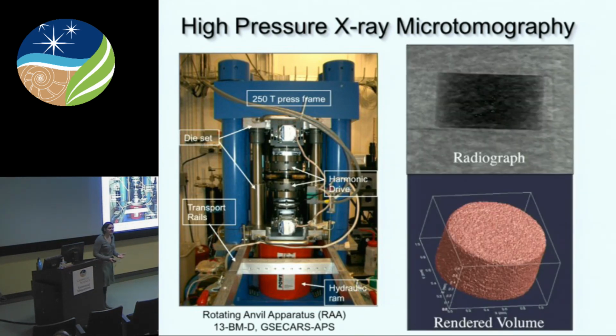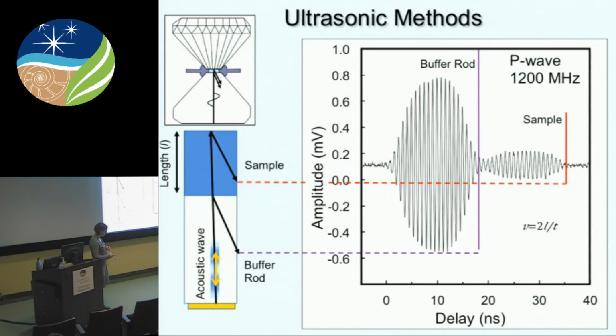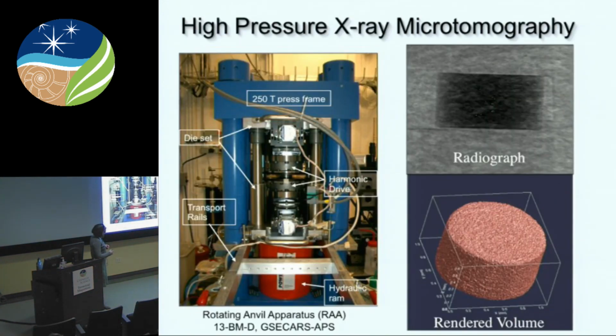So microtomography is exactly like all the other types of tomography, where you take a series of radiographs as a function of angle through the sample. For medical CTs, you move the source, and here we actually spin the sample itself, which is something that makes this press so unique. Once you have a series of rotational radiographs, you can then convert that into angular information that you can use to create horizontal slices that you can then stack to construct a three-dimensional rendered volume. And so that's what we have here.